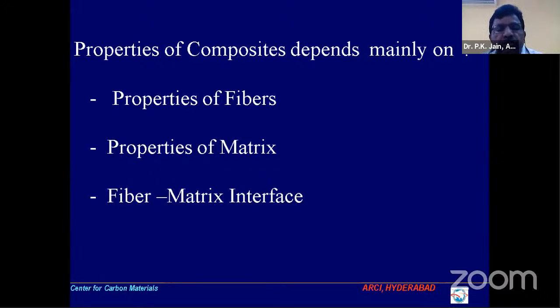Now, when you keep the properties of fiber constant, in India we don't make carbon fibers, we always import. People know, though you are from the aeronautical department, the Toray based T300, different grades of carbon fibers are there. The matrix of course we make, but the high grade, special grade epoxy, called Araldite LY 556 or grade 953, which is an aerospace grade, is a Ciba-Geigy product. All those things are common, but still we are not getting the properties we are supposed to get, and different groups will have different properties because of the processing difference, and the interface of fiber and matrix is very, very crucial.